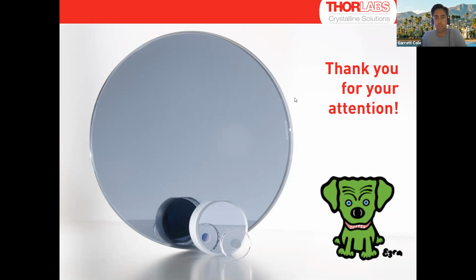I will point out though, at volume, it should scale nicely. Production MBE chambers are large. We can deposit over a very large area. We can make hundreds or thousands of coatings, discs, depending on the diameter, and transfer to hundreds or thousands of substrates. At that point, you could bring the cost way down, right? Typically, we grow on smaller substrates in a big production system to pay for that whole crystal growth run. And if we make 4 optics, you've got to pay for that whole growth run. So let's say again, right now, $5,000 to $7,000 per optic. If you want to go to high volume, I could probably push it to $1,000 per optic. That's the nature there. And I would say for those who have an ion beam sputtering background, it's somewhat comparable for custom run costs. But yeah, that should cover that.